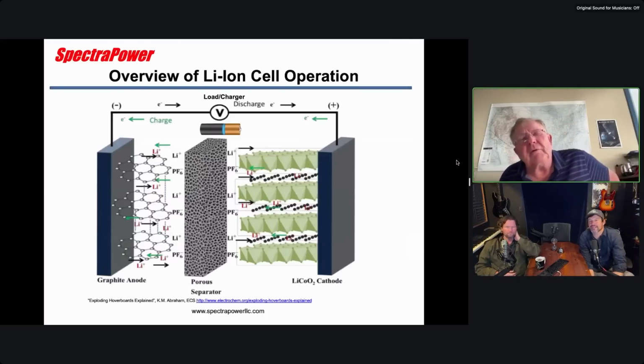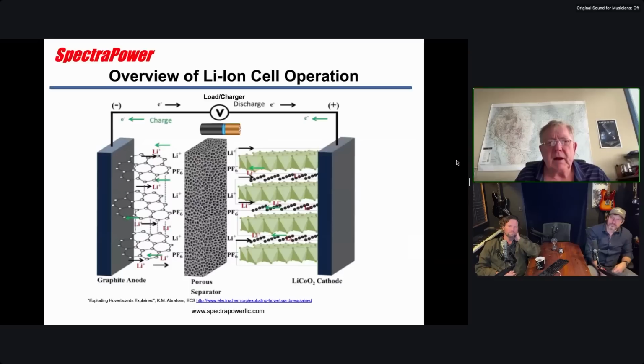Yeah. So I was going to mention that too. Typically the charge cycle for lithium-ion is constant current to constant voltage, CV charger is what you'll see. The constant current is a specified rate, and it holds the current at that rate. So, if you're going to charge at 1C in a 1 amp hour cell, you'll apply 1 amp. You'll limit the current to 1 amp so it can't try to charge too quickly.